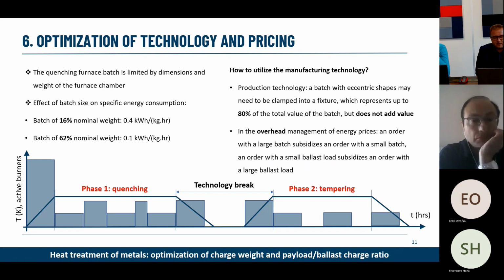We fixed the quenching and tempering cycle duration as constant, and we repeated the same exercise with a different batch, again with constant duration, but with 62% of the nominal theoretical limit of the furnace that you can plug in. Overall, in the first case, to perform the quenching process, we spent 0.4 kilowatt hours per kilogram per hour, so it's like normalized energy spent. And in the second case, we spent only 0.1.